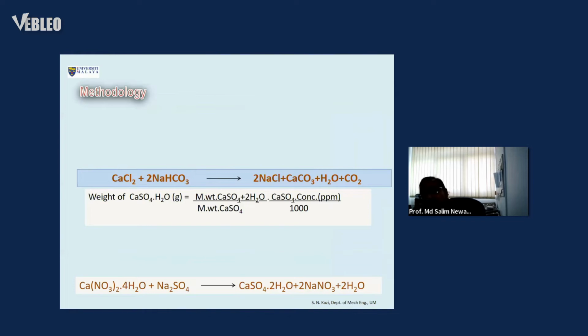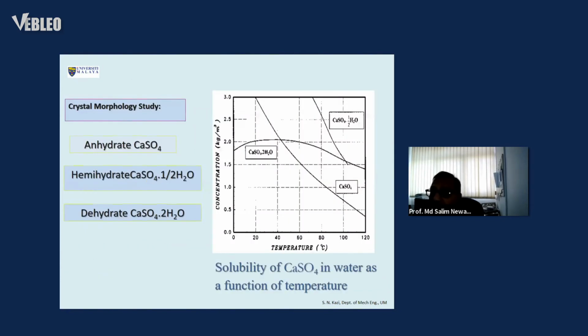We have several setups to do this type of experimental test run. As it's difficult to dissolve calcium sulfate and calcium carbonate in water, it's done through a reaction. Calcium nitrate tetrahydrate is reacted with sodium sulfate, and then calcium sulfate is formed. Similarly, with calcium chloride and sodium bicarbonate, calcium carbonate is formed. But the sodium chloride here is not doing anything, because it's a normal soluble salt. So that's how this work is being done here.